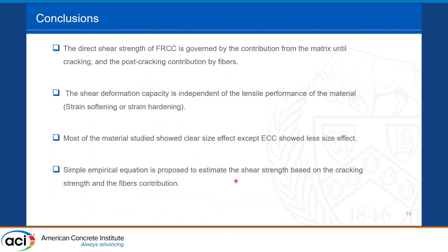To conclude: the direct shear strength of fiber-reinforced composites is governed by the matrix contribution until cracking and the fiber contribution after cracking. The shear deformation capacity is independent of the tensile behavior, whether the material is strain softening or strain hardening. Most materials studied showed a clear size effect, except ECC which had a lower size effect. A simple empirical equation is proposed to estimate shear strength based on matrix and fiber contributions.